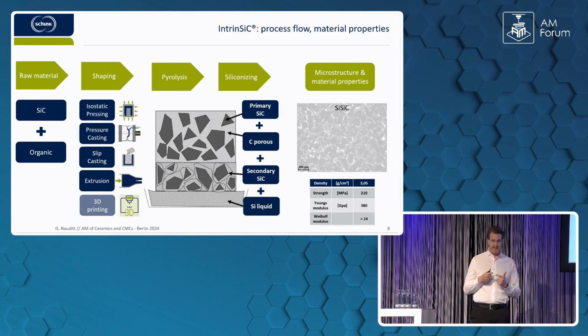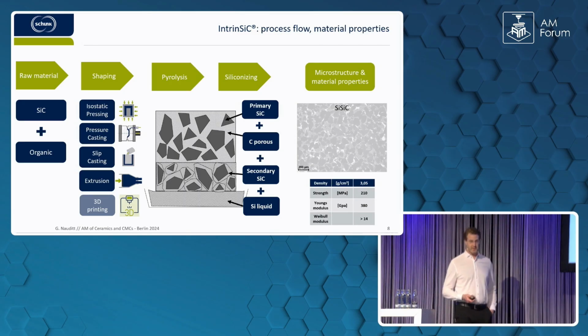Around that we have light gray areas, which is the secondary silicon carbide, and the pores there are filled with the free silicon. The free silicon remains in the pores. And this gives us a very stiff material. If you look at the value, 380 gigapascal, that's quite good.